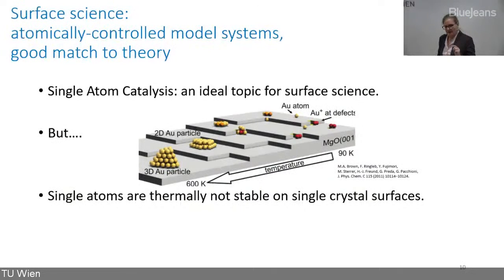Except for one little caveat. It turns out when you put one of these metals on a single crystal, which are typically our model systems, and you heat them up to the temperature where the reactions happen, these particles don't stick, they don't stay as single atoms. What they do is ball up and make small clusters. So unfortunately, the single atoms are normally not thermally stable on most single crystal surfaces.